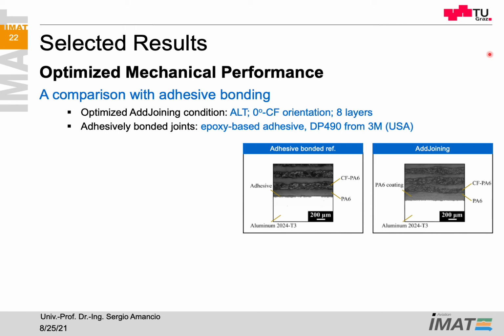And here is a cross-section showing the details of the adhesive bonded joint and the AddJoint. Basically, the difference is that we prepared the aluminum in advance, and we printed the composite in advance. Then we deposited the adhesive and cured it following the instructions of the adhesive producer and the guidelines of the aircraft industry. And then we applied the process to produce the AddJoining. So in this case, the alternated configuration with 0 degrees orientation in the carbon fiber oriented plies, and we had 8 layers in total.